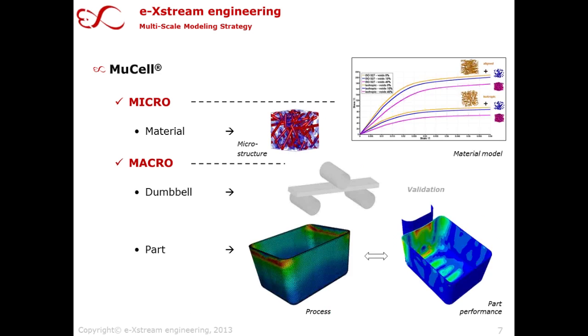So this is our generic approach, and we even cover new topics. A new topic for us, in terms of short fiber reinforced plastics, could be MuCell, so the foaming of the material matrix, and we take exactly the same approach. So we start with a representation of the microstructure to understand the material better, the mechanisms in the material. We derive a material model, and here the material model is a multi-dimensional one. So it's not only sensitive to the fiber orientation, but at the same time to the amount of voids in the matrix. So this can be locally distributed in the MuCell process as well.